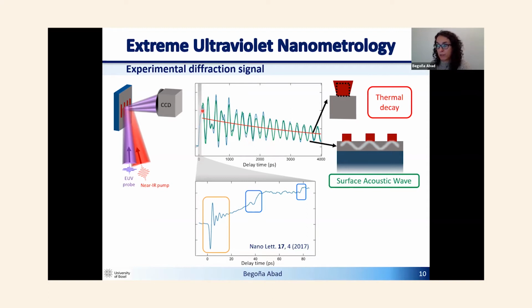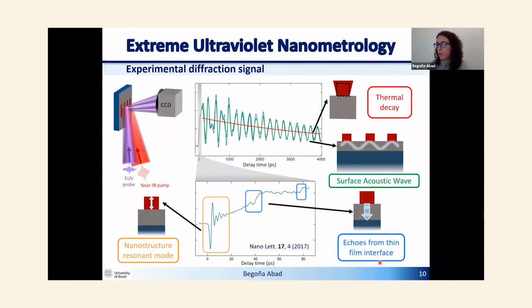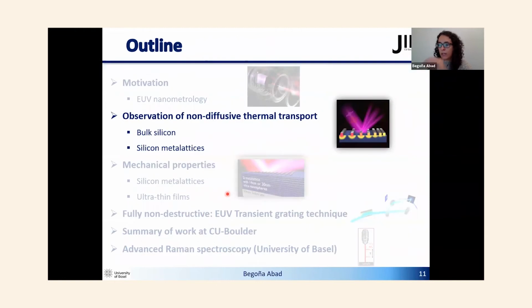Finally, if we go to very short time scales, we can see these oscillations that are given by the nanostructure's own resonant mode. And finally, there are other features that happen when we have a thin film on top of a substrate, and those are just echoes. It is a longitudinal acoustic wave reflected off the interface. Okay, so with this technique, we were able to study thermal transport and also mechanical properties.